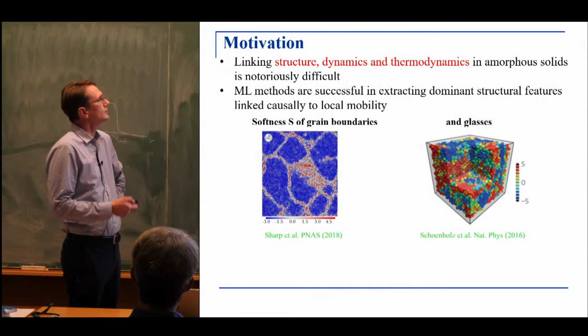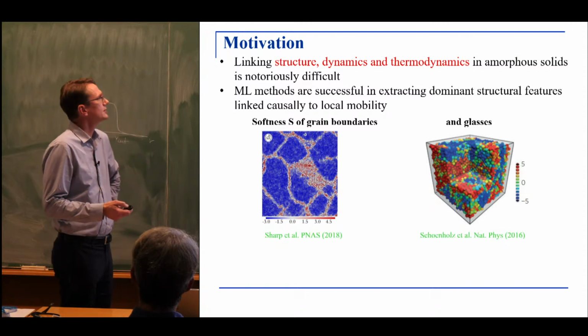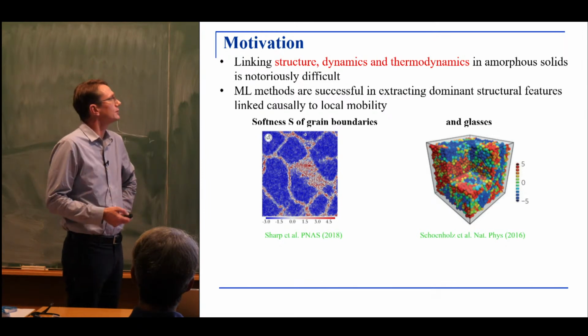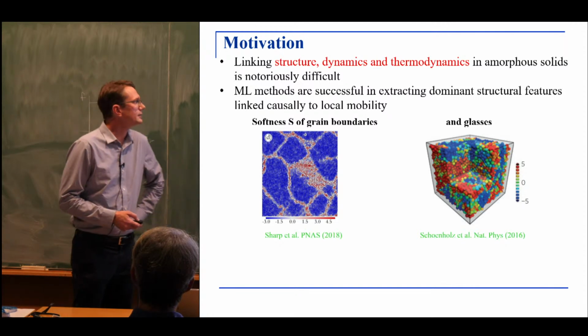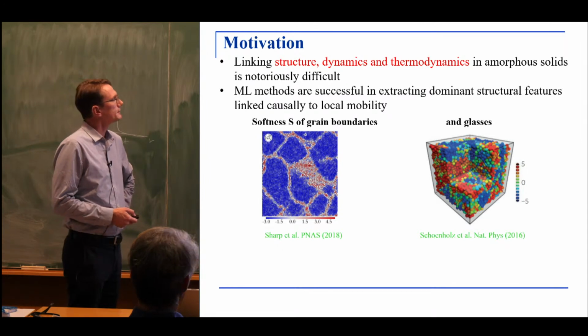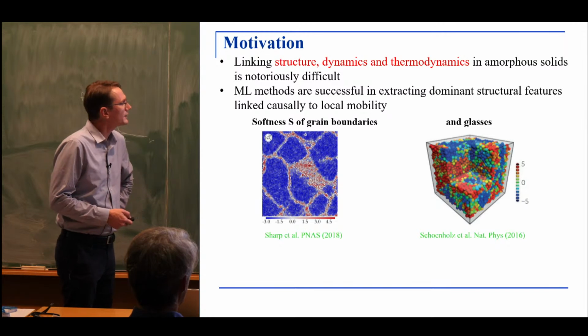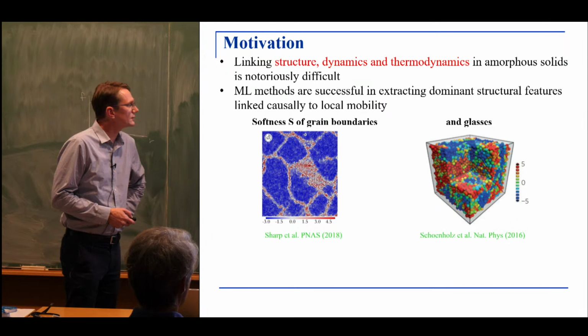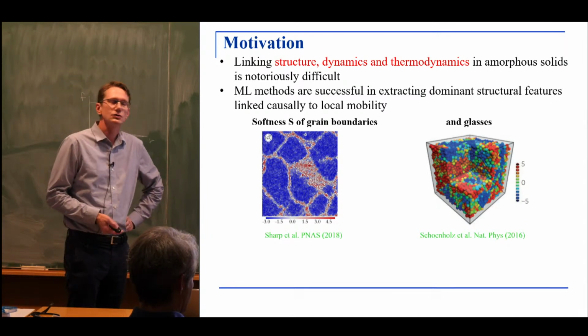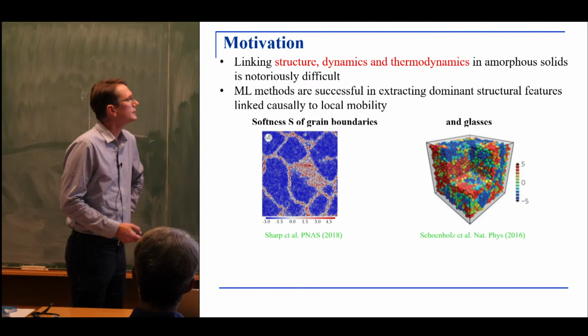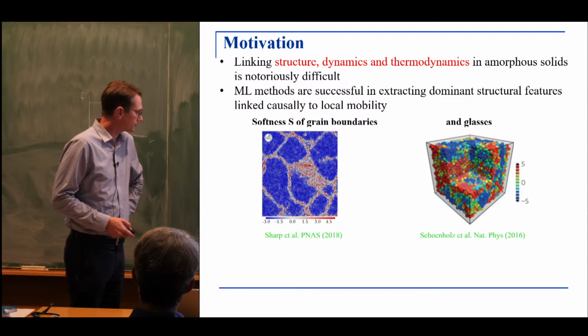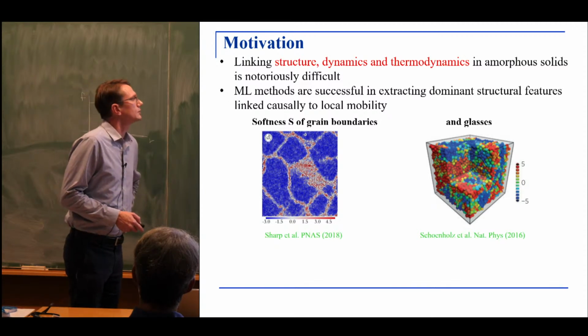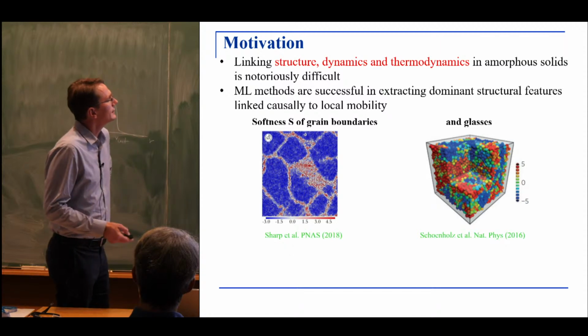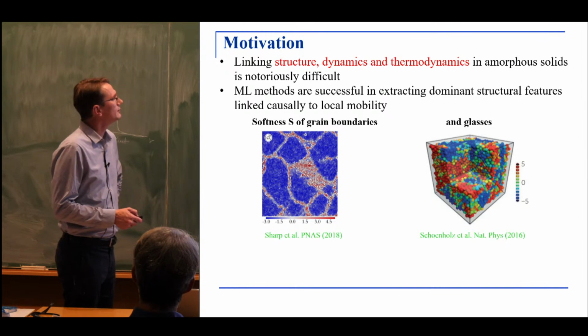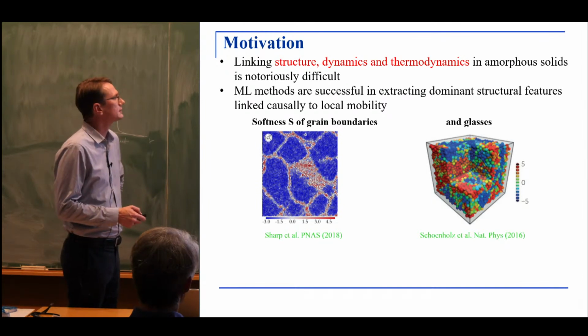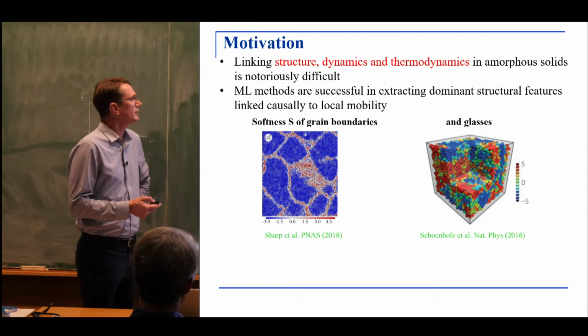The motivation for this is that we know that machine learning methods are very good at extracting structural features out of a complicated data set. The question that interests us is whether those features can be linked causally to local mobility. One of the concepts that was introduced about 7 years ago, that gave us hope that such an approach would indeed be fruitful, is this idea about softness. This is a classification of particles into slow-moving and fast-moving particles. One has to train a system, in this case a simple division into a hyperplane of fast and slow-moving particles. If one does that, then one could, for instance, predict that fast-moving particles would be found predominantly at the interfaces between grains in a polycrystal, or in a glass would agglomerate into clusters that are separated from slow-moving particles.